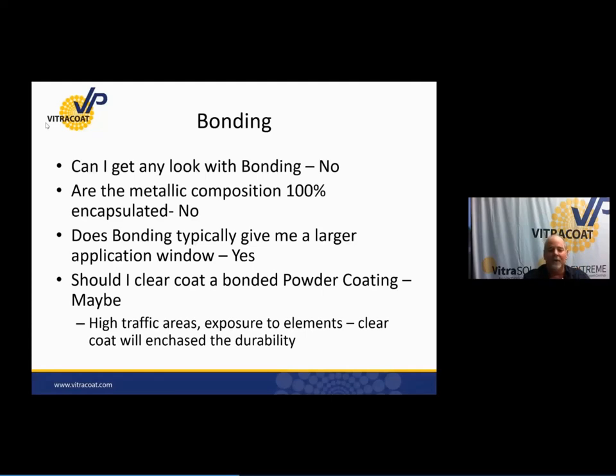But if exposed to the elements, if it's a high traffic area, if it's being handled a lot, a clear coat will absolutely enhance the durability of that even bonded product. So be careful. Bonding is a phenomenal way and a great way to get the looks you're looking for with a broader application window, but you still have to be careful because there's metallic in it that can be susceptible to things because it's free metallic.